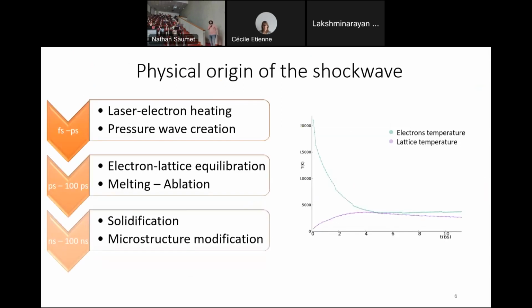So the physical origin of the shock wave in the femtosecond laser peening is the disequilibrium between the electron temperature and the lattice temperature. Why? Because at the femtosecond scale, only the electrons see the laser, and so the electronic temperature increases a lot, very fast, and during a few picoseconds there is a disequilibrium between the electronic and the lattice temperature, which leads to the creation of the shock wave and its propagation into the bulk. Then the equilibrium is reached within a few picoseconds.